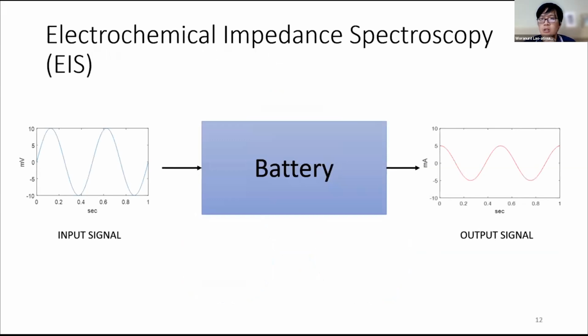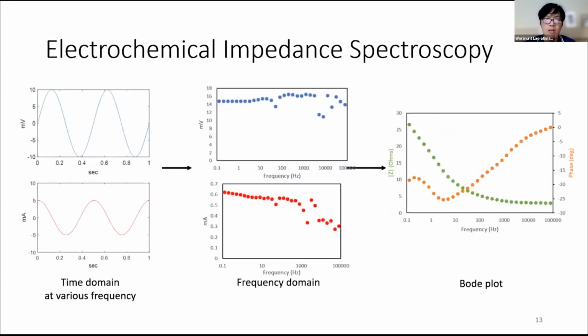For EIS, or electrochemical impedance spectroscopy, the battery is injected with a sine wave signal as input. In this case, it is injected with a sine wave of voltage, and then the output signal, which is the current, is observed. The voltage and current respond in the time domain at various frequencies, so we can transform them into frequency domain data, and then the impedance data can be calculated at each frequency as shown in the Bode plot.